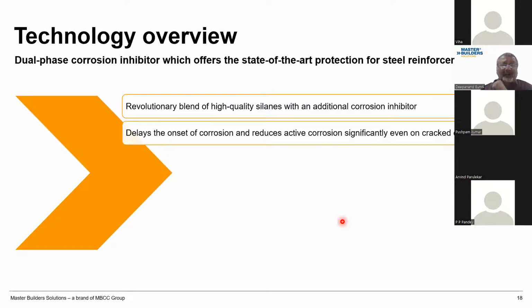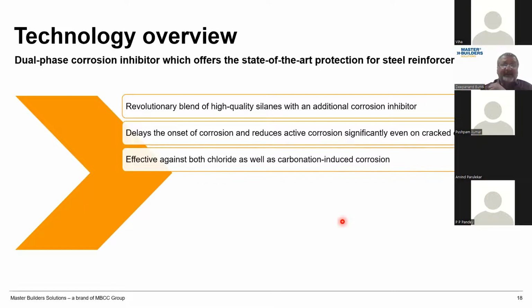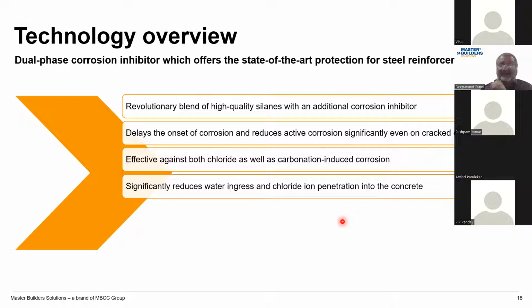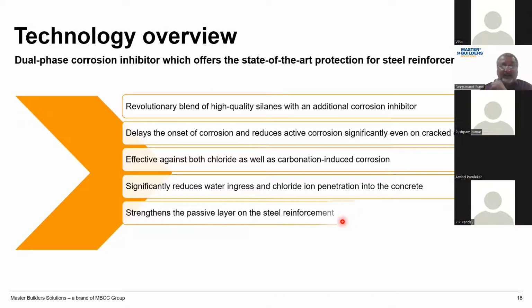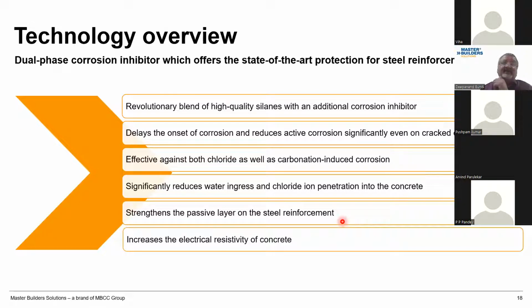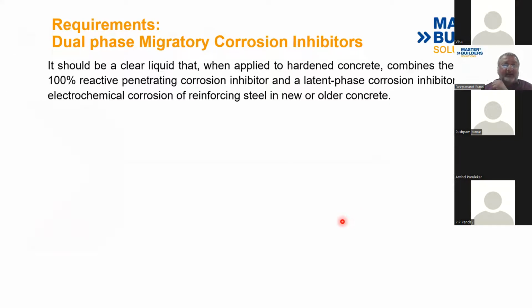It delays corrosion and reduces the active corrosion even on cracked concrete. As I said, it's effective against both chloride as well as carbonation-induced corrosion, significantly reduces water ingress, and strengthens the passive layer on the reinforcement. So it goes and forms a layer on the reinforcement bar, increases the resistivity of the concrete. These are the important highlights. The requirements are to be a clear liquid that when it is applied on a hardened concrete combines the power of a penetrating inhibitor and a latent phase inhibitor. Right?